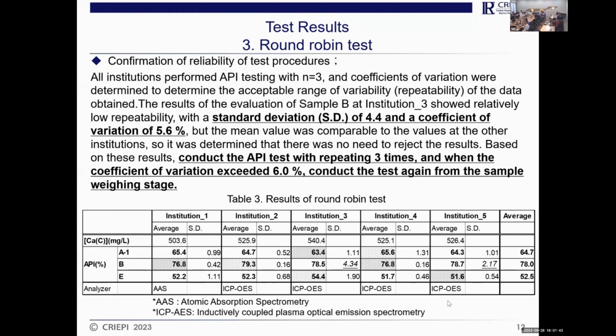The next figure shows the result of a round-robin test we operated with 5 institutions. I delivered 3 fly ash samples named A1, B, and E. And the upper row shows the CCa, the concentration of calcium ion in the standard specimen, the standard line. From this data, all institutions have the same result. And the next line shows the API; each of A1, B, E shows almost the same. But I noted the SD, the standard deviation.